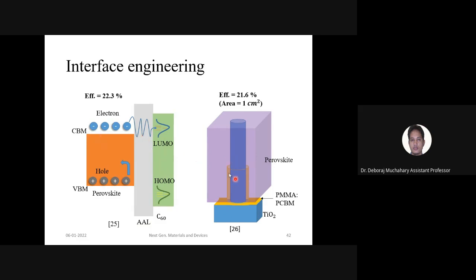So that is why they have used this new technique. Instead of blocking the layer completely, meaning placing the whole layer uniformly here, they have done something like C60 or TiO2, which is also an electron transport layer. They have made some nanostructures like this. The advantage of this structure is that there is this perovskite layer on top, and this is the TiO2. Instead of completely putting a blocking layer here, they have made a small hole in between, where they have inserted the TiO2 nanostructure. The TiO2 nanostructures will be inserted inside and connected to the perovskite. This way the reduction of the series resistance is good, right? So the series resistance of this region will be reduced, and that way they can improve these things.